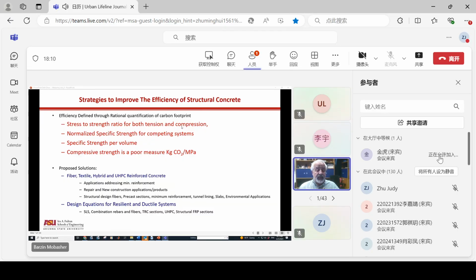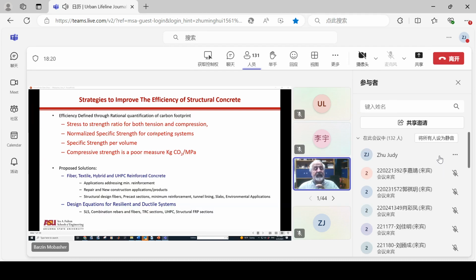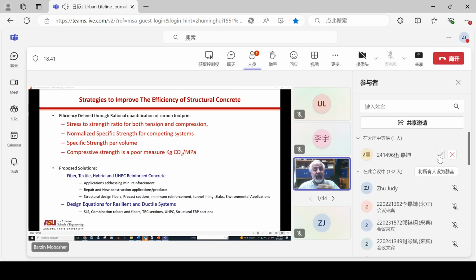Concrete is extremely good in compression, but it's awfully brittle in tension, which means that we have a very low tensile capacity. So we need to normalize the specific strength. We need to be able to characterize the material property not based on its compression properties only, but also the tension properties. If we can improve the tension properties, we can definitely carry a lot more load, because tension failure is the dominant mode that is a showstopper that doesn't allow us to further use the amount of concrete.